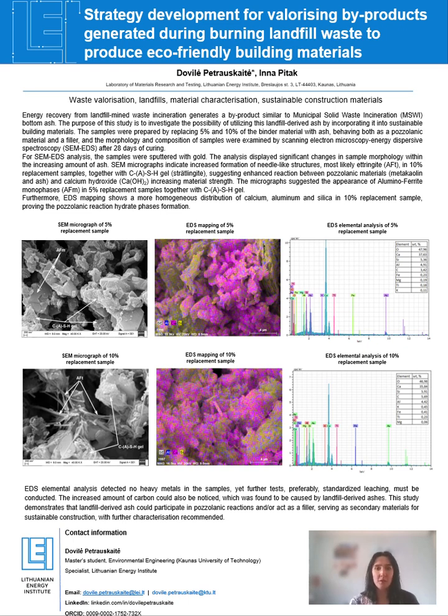While excessive carbon may slightly reduce the pozzolanic activity, it could also improve thermal insulation and reduce the density, which may be beneficial for lightweight materials. So also further standardized leaching tests are recommended to confirm long-term stability and environmental compliance.